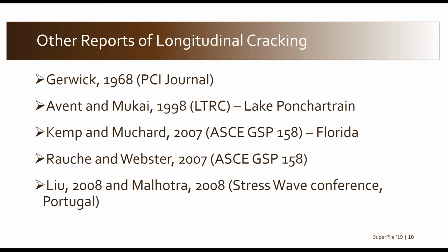Diving into the literature on this subject, we found that it's been documented for 50 years that these cylinder piles are commonly found to exhibit this type of longitudinal cracking. In fact, that second report by Avent and Mukai in 1998 points out that the two structures that I highlighted with photos at the beginning both have longitudinal cracks in the cylinder piles that have been discovered since then, and so do a number of other examples of cylinder piles as documented by these other reports.